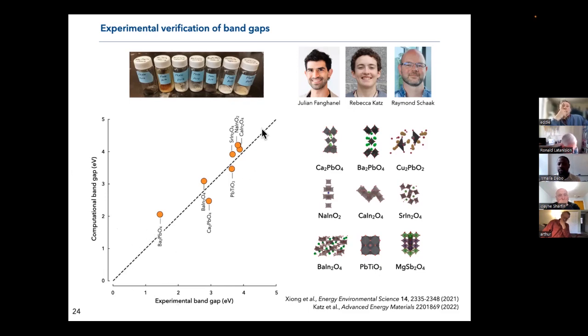And using this parity plot, compare that with the computational gap that is obtained from density functional theory. And what you can see here is that the band gaps that we obtain are pretty consistent. So everything lies on this diagonal line, meaning that you have a one-to-one correspondence between the experimental and computed band gap for most of the material that we had. And so we are very happy to see that.